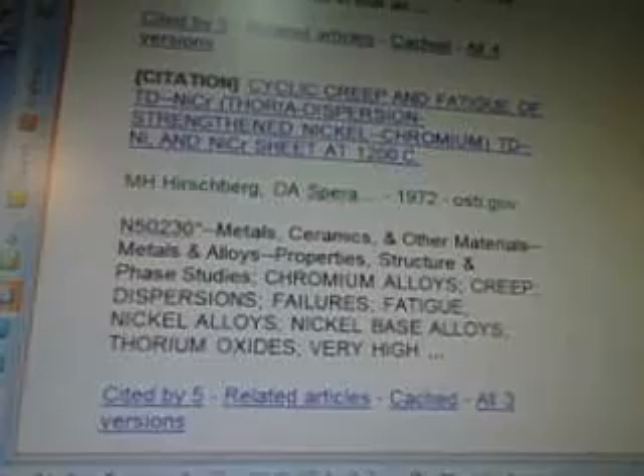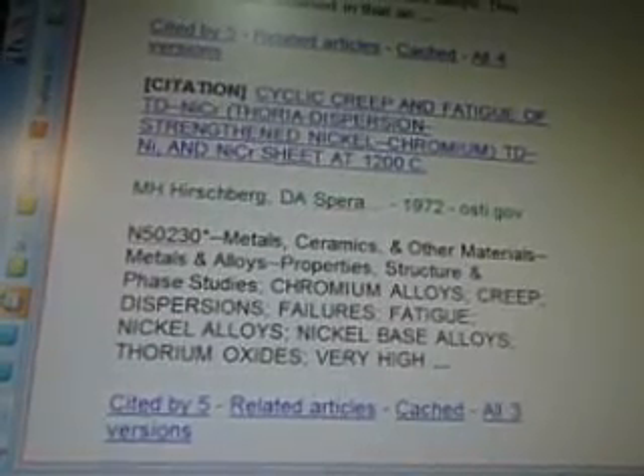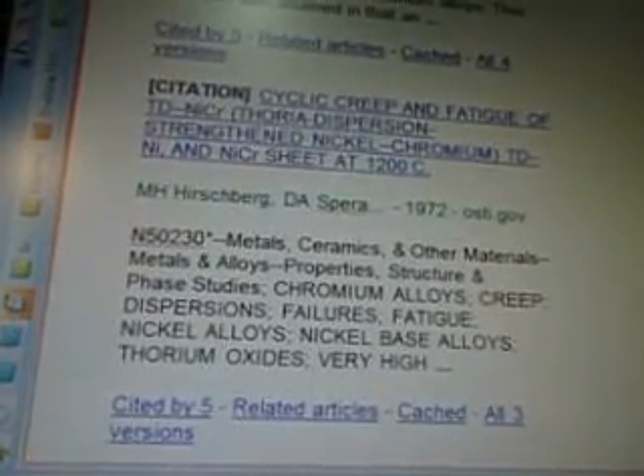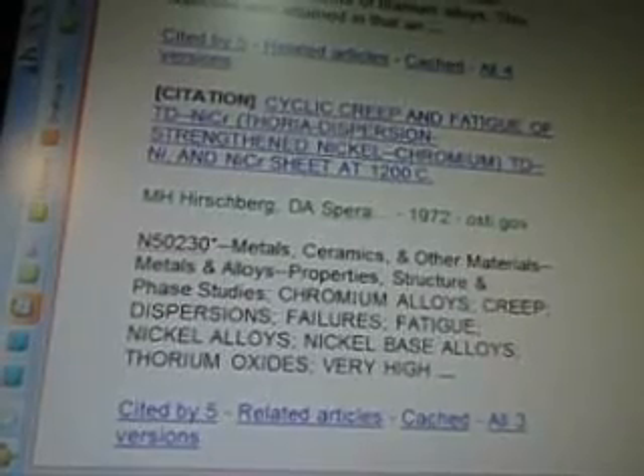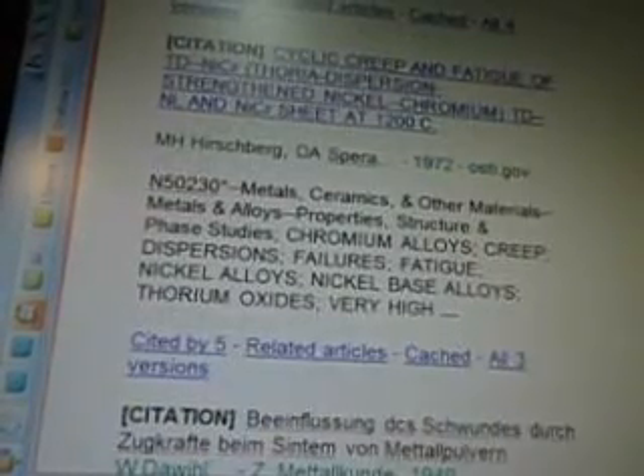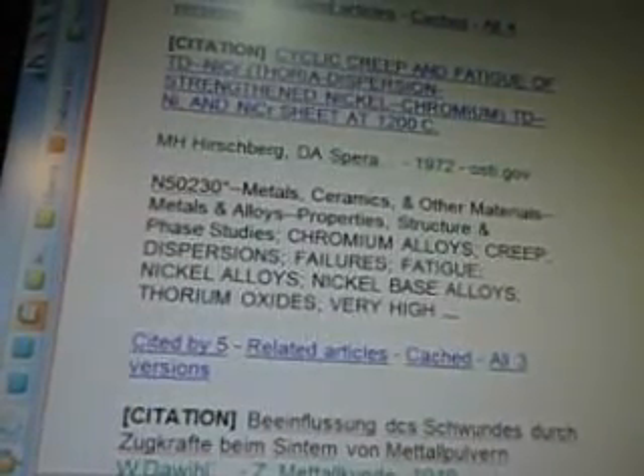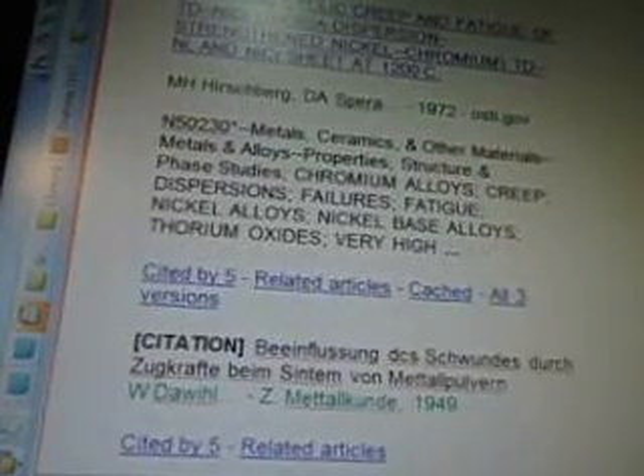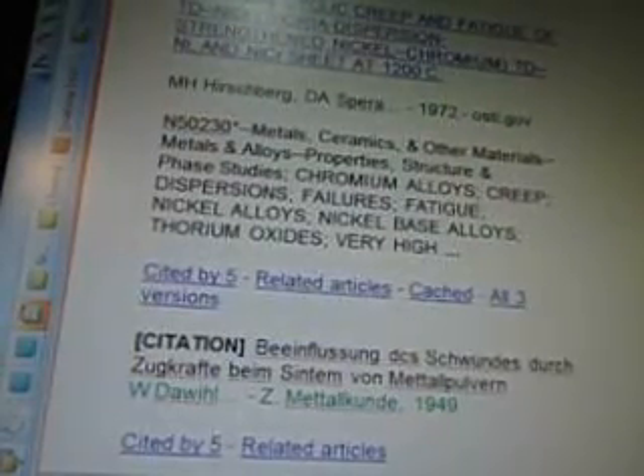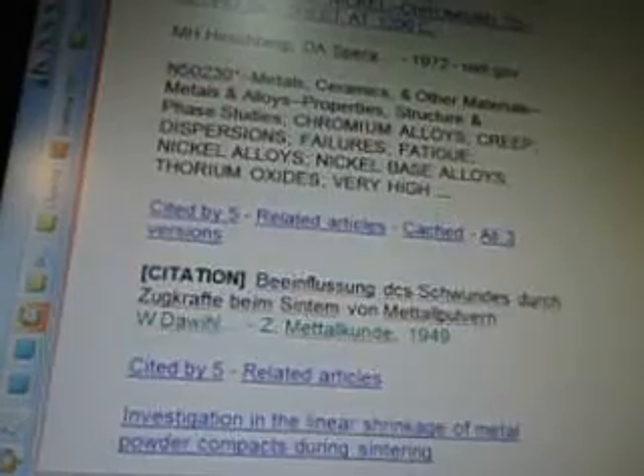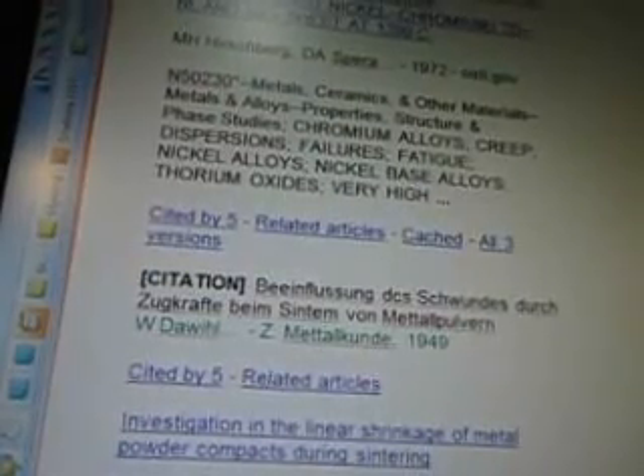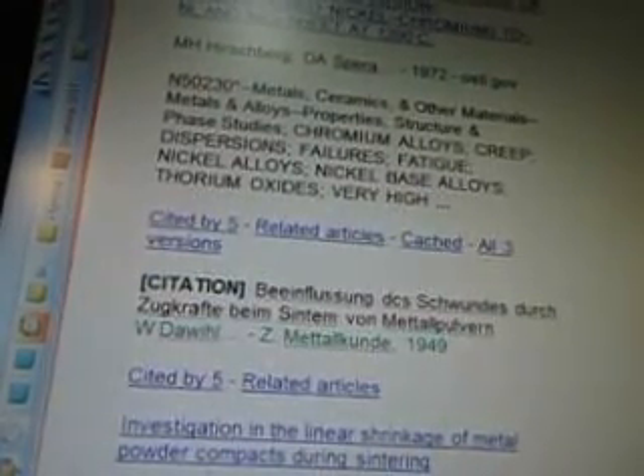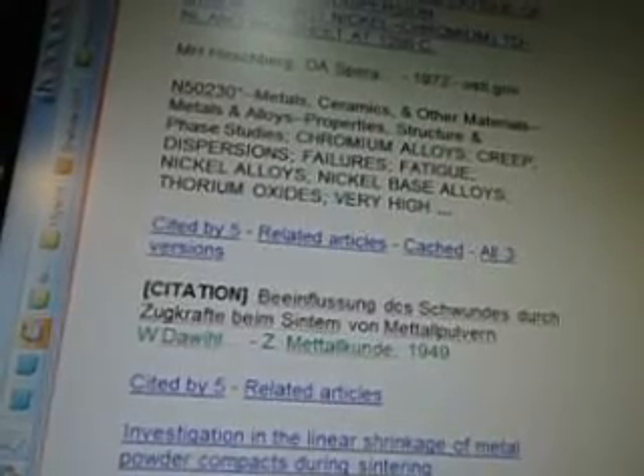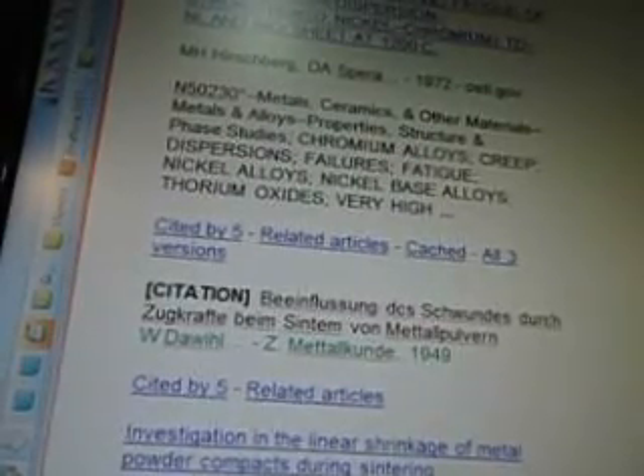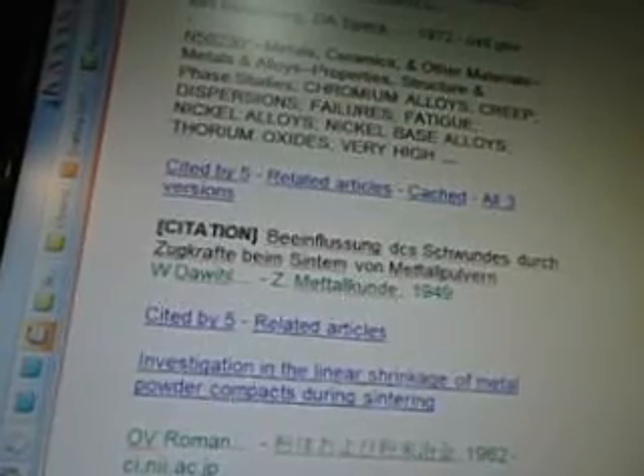Next is cyclic creep and fatigue of TD-NiCr, thoria-dispersion strengthened nickel-chromium, TD-Ni and NiCr sheet at 1200 degrees Celsius. M.H. Hirschberg, D.A. Spera, 1972, OSTI.gov, N50230, metals, ceramics, and other materials. Metals and alloys, properties, structure, and phase studies. Chromium alloys, creep, dispersions, failures, fatigue, nickel alloys, nickel-base alloys, thorium oxides, very high.